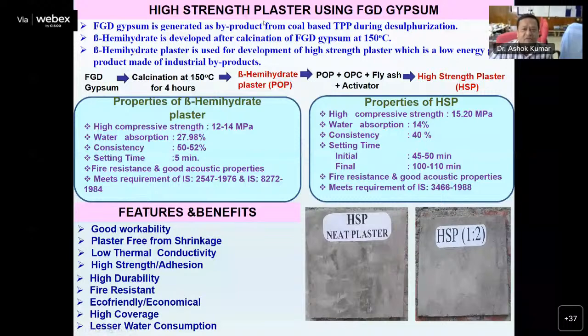The next binder which we have developed is the high strength plaster using FGD gypsum. FGD gypsum is generated from coal based thermal power plants using desulfurization. To develop this plaster, the FGD gypsum is converted into the hemihydrate plaster by calcination at 150 centigrade, and then it is blended with OPC, fly ash and activators. This high strength plaster has a strength of about 15 MPa and consistency of 40%. It can be used for exterior as well as interior purposes.